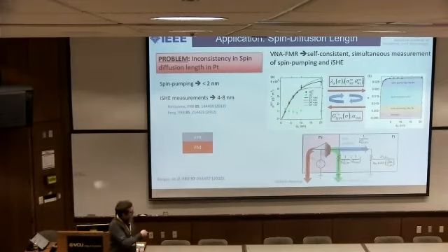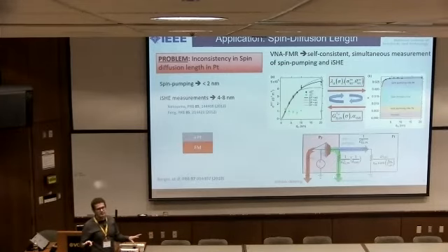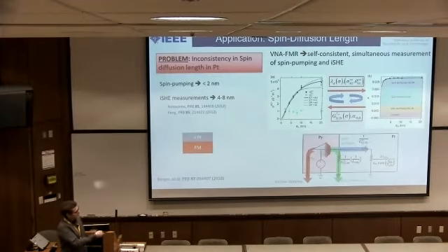So remember that for the spin pumping, of course, we get this spin current that goes into the platinum. That's what generates the spin orbit torques. And then we get this loss term at just the scattering at the interface, which we call spin memory loss. That's angular momentum that's just lost. It's gone forever. So the problem is that in spin pumping measurements, we cannot distinguish between the spin pumping and spin memory loss. So we're measuring the summation of those. And it turns out the spin memory loss is actually dominating that process.